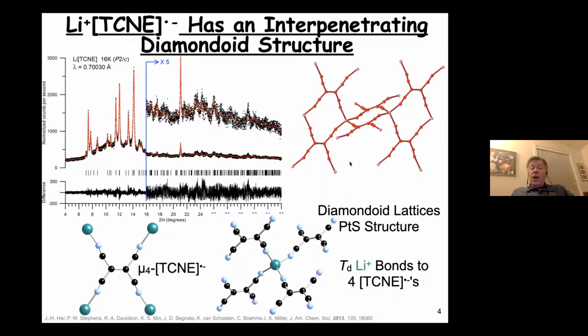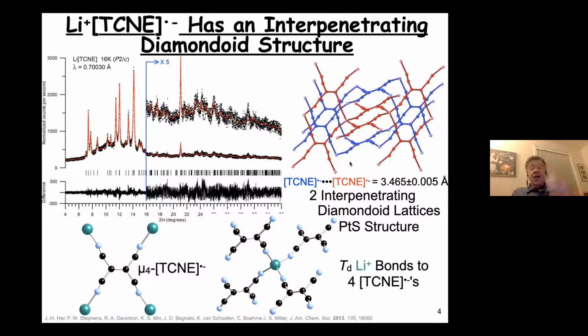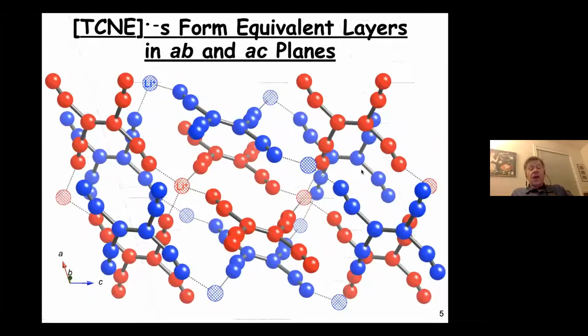And in fact, you have a second interpenetrating lattice illustrated in blue. The closest distance between TCNEs is at the van der Waals limit, a little more than 3.4 angstroms. If you look at the 2 interpenetrating lattices, you can see the lithium is tetrahedral. The red lithium has 4 red TCNEs, the blue lithium has 4 blue TCNEs, and they form stacks and layers in the AB and AC plane.